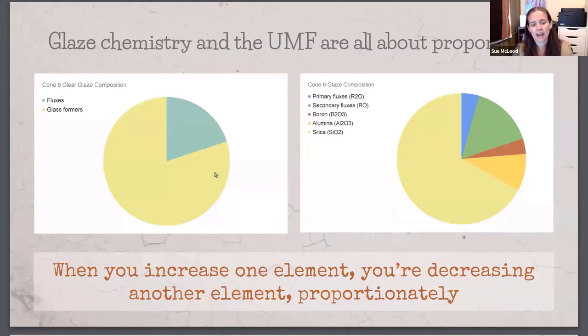So just a reminder that when a glaze recipe is the whole pie, the whole circle, this little section here represents the fluxes. Ideally, for durability, we want to have a big section of glass formers and then a smaller section of fluxes. We don't want to overflux the glaze because the glass formers are what make the glaze nice and durable, a strong glass. So now I take the glass formers and break them down into silica, alumina, and boron.